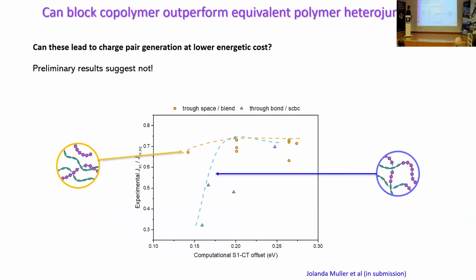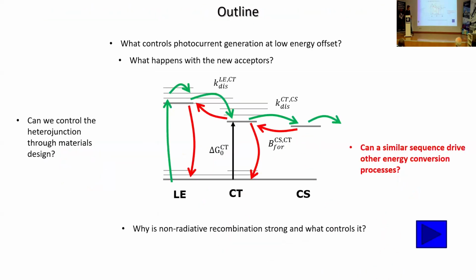To push it to the edge, we then thought, okay, let's make a comparison between these block copolymers and exactly the same materials, but in a polymer-polymer arrangement, and see what happens now that we know how to work out the offset. How does the photocurrent depend on the offset? And in fact, we find that it looks, from what we've done, as though there's not an advantage of the block copolymer arrangement over the polymer-polymer arrangement, because in the end, they get limited. So it's a bit disappointing, but that's what we got. And it's telling us, yeah, we still need a bulk heterojunction to get a high photocurrent efficiency.